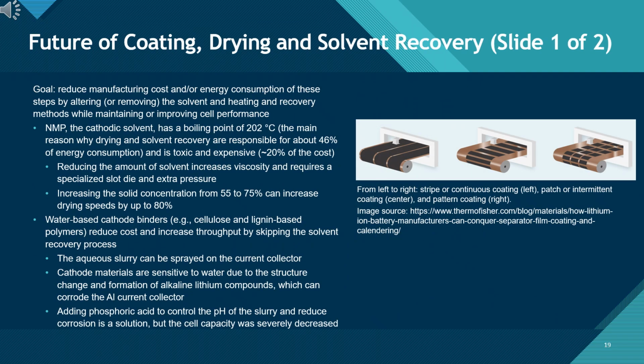Future of coating, drying, and solvent recovery, Slide 1 of 2. This slide highlights future directions to lower the cost and energy burden of coating, drying, and solvent recovery, three of the most energy-intensive steps in LIB manufacturing. Traditional cathode production relies on NMP, a costly and toxic solvent with a high boiling point, which drives long drying times and accounts for nearly half of the total process energy.